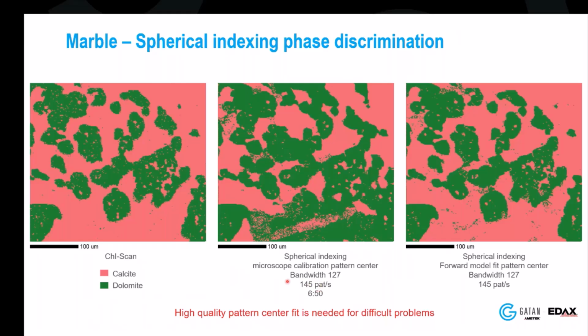I'm not going to talk about the bandwidth thing again, but realize that if you ever set up the Hough, the Hough-based indexing has, I think, 13 parameters. Spherical indexing has one, and it's just because of bandwidth. It's basically how it's measuring in frequency space. So the higher bandwidth you use, the longer it takes, but it's able to see finer-level details. But it's one of those crazy things I find about spherical indexing, that it really bends the learning curve for EBSD because the parameter space is so much smaller.